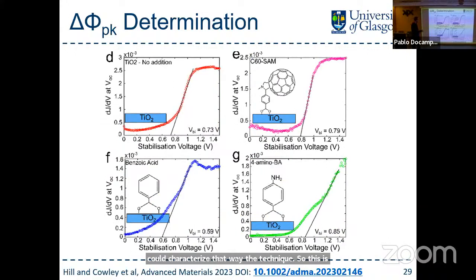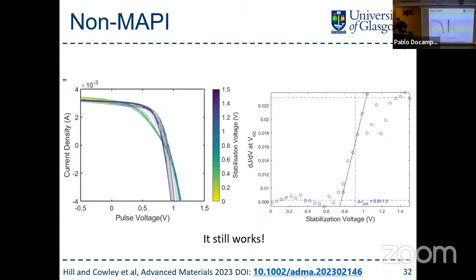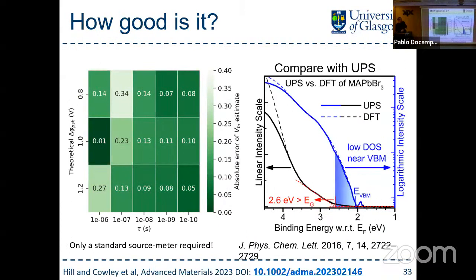We can show that depending on what you stick on the surface, you can tweak the potential, and you do end up getting different built-in potentials, which is really neat, because, like I was saying, the way you would normally characterize this is using UPS, which is actually not that precise.